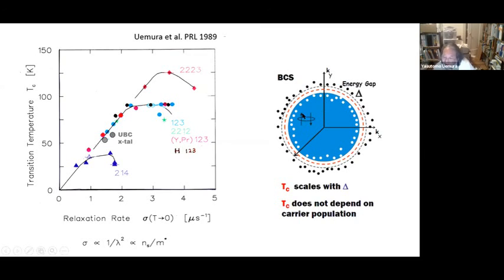So let's say if you have this gap, and then you can somehow reduce the gap size to half, your Tc will become half, but the superfluid density will stay the same. So this means that for BCS-like condensation, you would not expect much correlation between Tc and the superfluid density. Instead, we are seeing a very strong correlation here. And so in my opinion, this is one of the first indications of non-BCS-like behavior.